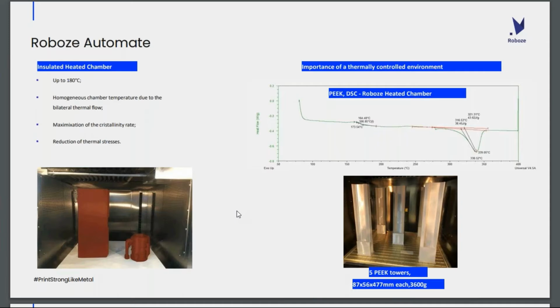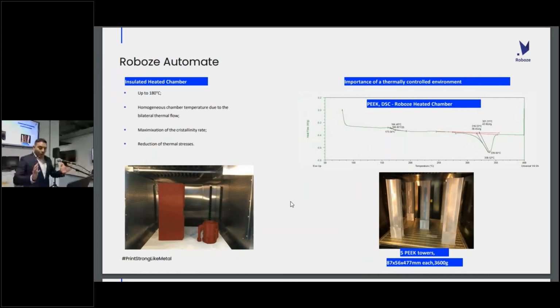So we did a study for an energy company where we printed these 5 PEEK towers, and we measured at 3 different heights the mechanical performances of these PEEK towers compared to where they were printed. And there is very little deviation in the data. That gave that specific OEM the opportunity to qualify the process for an extreme application in the energy business.